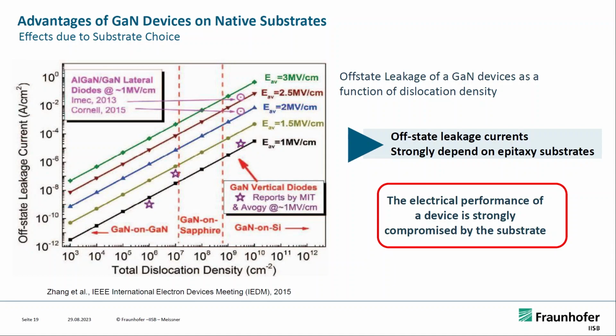Here you can see another plot for the effects of substrate choice. Off-state leakage current versus total dislocation density is sketched here. If you compare gallium nitride on gallium nitride, on sapphire, and gallium nitride on silicon, looking at the bare number of dislocations—not the types, whether they count or not, just the total number—you see that gallium nitride on gallium nitride really brings down your leakage currents.